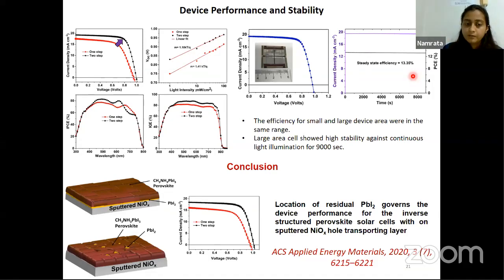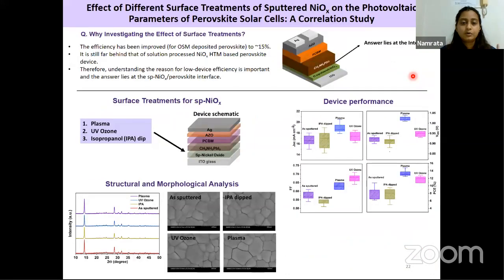So from the two studies, the cumulative conclusion we got is that the location of residual PbI2 governs the device performance for the inverted structure perovskite solar cells with sputtered nickel oxide hole transporting layer. So the next thing is to look at the surface of nickel oxide even more clearly. Since we have already figured out that the bulk defects in the perovskites are arising from the surface, we tried to change the conditions at the surface of nickel oxide before depositing the perovskite.